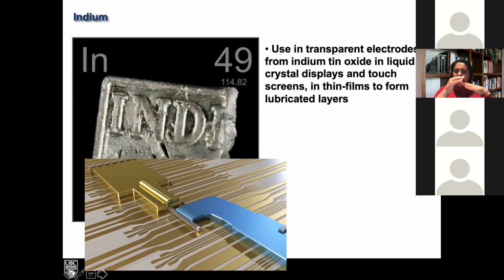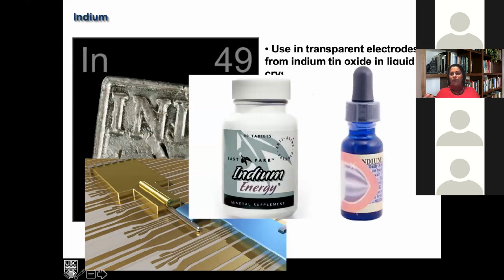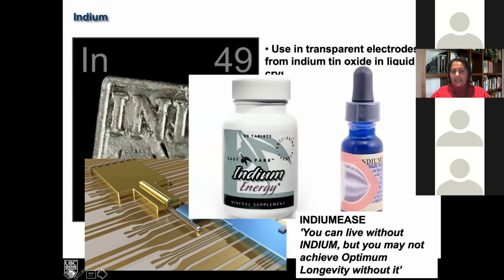But the other question that I get about indium is, is it toxic? And the toxicity of heavier main group elements is entirely dependent on their oxidation state. So indium generally is found in the trivalent oxidation state, and in that state, it's used as indium oxide pills that you can take or drops that you can take. And I'm not suggesting this, but this is what the marketing for this material is. This one company says you can live without indium, but you may not achieve optimum longevity without it. So I keep you forewarned that you should be taking your daily dose of indium according to this company. Please don't. But just in terms of toxicity, indium-3 is taken internally and is not toxic.